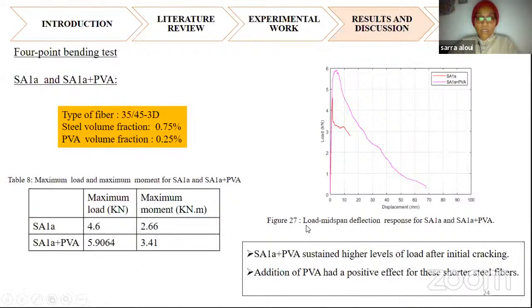For the SA1, here we can say the specimen with PVA has a high maximum load and maximum capacity. We can see that the PVA has a positive effect for this type of specimen. For the second one, they have a very nearby maximum load. So we can say that the addition of PVA has a neutral effect for this type of steel fibers.